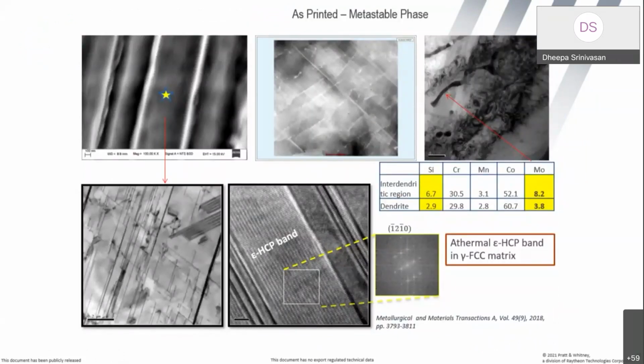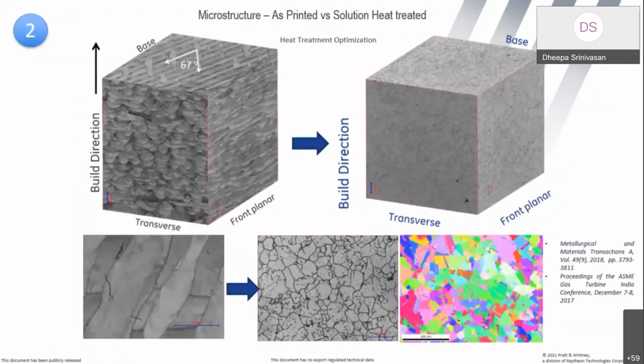Namely, what you have is a microstructure which is metastable. I've been able to get a uniform isotropic recrystallized microstructure by combining the post-weld heat treatment process with the heat treatment that is necessary for this particular alloy via additive manufacturing. So the microstructure is isotropic. This is the electron beam scattered EBSD diffraction map, which shows you there is no preferential texture or orientation after doing this heat treatment in this particular condition.